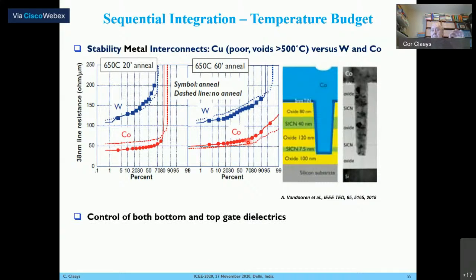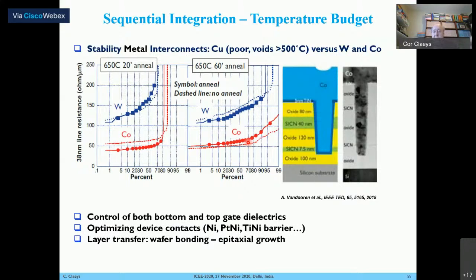In general, you have to be careful with temperature budget because you have to control the quality of the top and the bottom oxide. If the temperature is too high, you get a recrystallization of the bottom gate dielectric, which you don't want. You have to optimize the contacts in both types of devices. The layer transfer can be done with wafer bonding, or more elegant, in my opinion, by epitaxial growth. And you have to be careful with dopant activation.